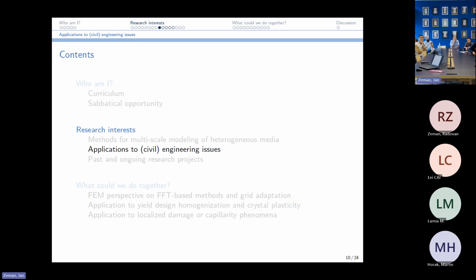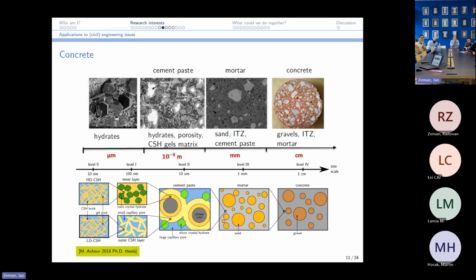Now, since I'm assistant professor at the GM laboratory, I've been working a lot on concrete. Concrete is a really heterogeneous material, which is studied a lot in our laboratory. You have heterogeneities ranging from the centimeters, like gravels, millimeters, the sand, micrometer would be the hydrates and the biggest unhydrated clinker core. And if you zoom in that cement paste, you would see hydrates which have sizes which can range from the micrometer to a few nanometers.